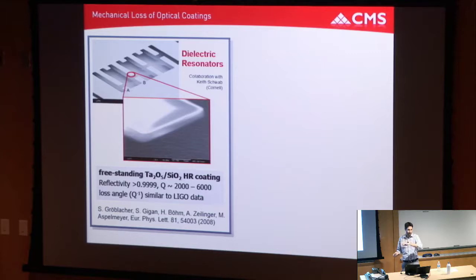So this is a little diving board of just the interference coating itself. We can get very nice optical quality. We could get the finesse we needed in our cavity, but we would get these very low Qs of a few thousand. And this work was done in the 2006 to 2008 timeframe. If we had been smart, like you should, and read the old literature, we would have known that LIGO had already shown in the late 90s that these materials had limited Qs, limited mechanical quality factors.